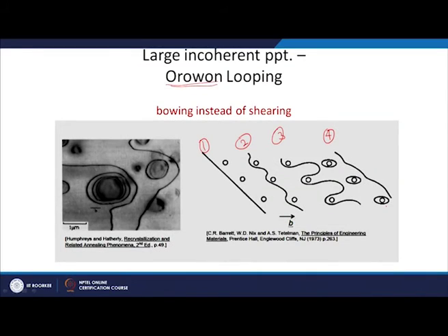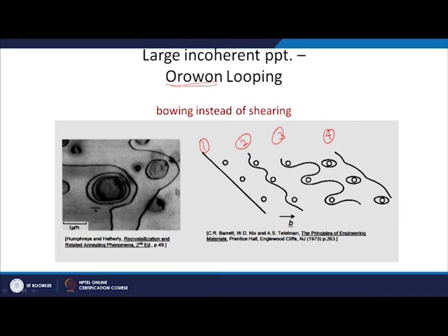Now, how does the strengthening come through this process? When one dislocation moves, it has left this loop around the precipitate. So, earlier there was the interparticle spacing, the distance between the precipitates. Now when the loop is left behind, the effective distance between the particles has become L prime, and L prime is less than L. So, when one dislocation goes through and leaves the loop, my distance between the particles has decreased. For the next dislocation, when it comes, it sees a smaller interparticle distance. So, it will become difficult for it to loop through.